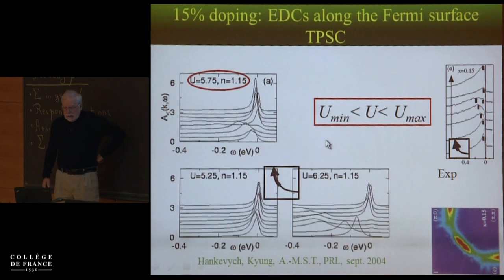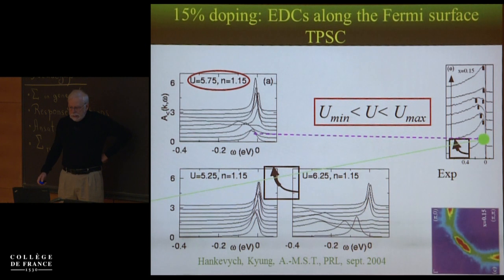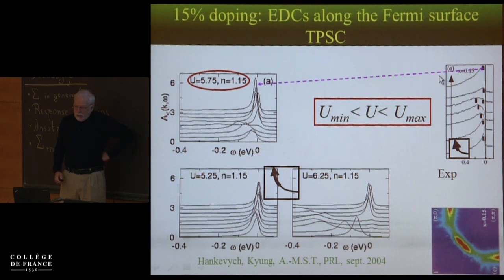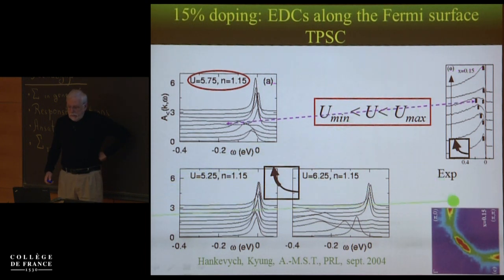Now, what are the results of the calculations? So this peak here is what we see in the calculation. This peak there is what we see here. And the clear difference is that we don't have these long tails here. I don't know why. I mean, they could come from multiple scattering, or it could be really a defect of the calculation, but we don't have these long tails. On the other hand, if you look here where we have weight that is missing, you see that the weight is pushed away from omega equals 0. It's the same thing that you see here. And you see even the experimentalists have identified some peak here, which corresponds to the end of this arrow. And there's another peak closer to the Fermi energy, which is this little bump here.